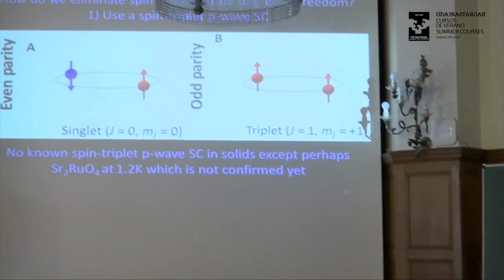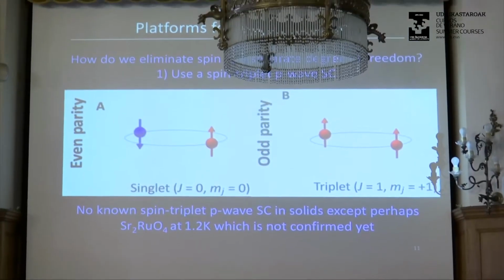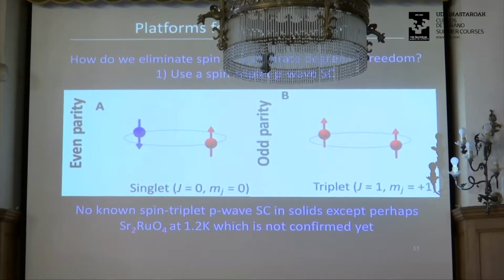So let me just show you a few ways. One is you can use a triplet p-wave superconductor. If you have a spin triplet superconductor, the pairs are composed of the same spin particles, two spin ups. And once you have that, you don't have to worry about spin anymore. Okay? So that's one way to get rid of spin. The problem with this is that there are very few known spin triplet superconductors.